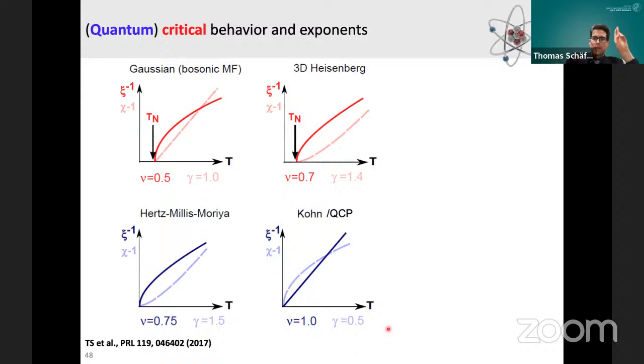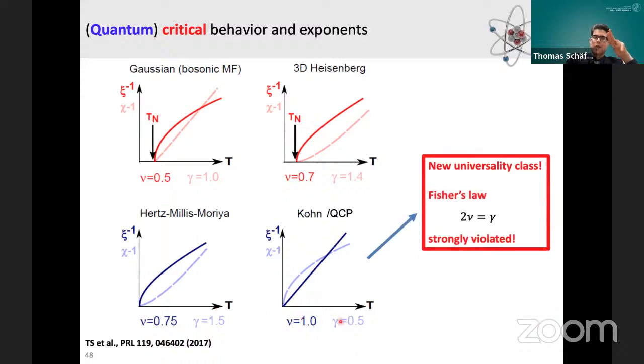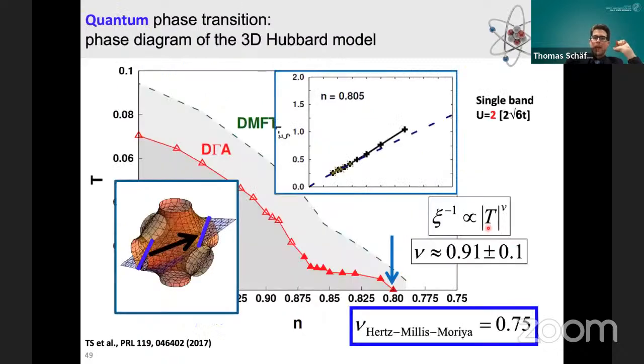The second thing, which is quite surprising, is also that the order of this universal exponent relation changed, namely the usual Fisher relation, which states that 2 nu should be equal to gamma, is strongly violated. Actually, it is reversed in this case. Let's go back to our numerics and check whether this could be true for our quantum critical point here. You would have these critical exponents with the error bars. This is the Hertz-Millis-Moriya, which is not fulfilled. However, the Kohn QCP seems to be fulfilled. As I said, it's quite surprising having this at strong coupling.